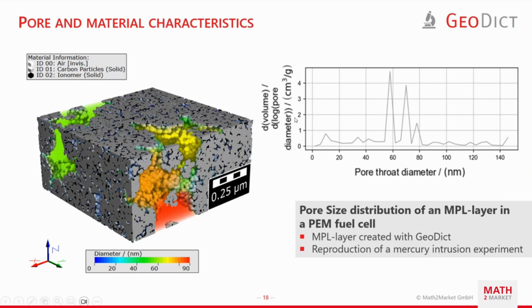And you get the exact same graph in GeoDict if you run a mercury intrusion experiment. Then you can compare the digital experiment with the real experiment and see, does it fit? If it fits, you're probably fine. And you can go one step further with the simulations, because with mercury intrusion, you only get the throats of the pores, or the sizes of the throats. And for the transport, it's also important to know how big the pore inside is, so the pore body. This is something that you can get with GeoDict, also for hidden pores inside of the material. We had that in the plenum talk earlier. And once you have validated your structure using experiments and digital experiments, you can rely on that and go one step further and use things that are not available in the experiment itself.